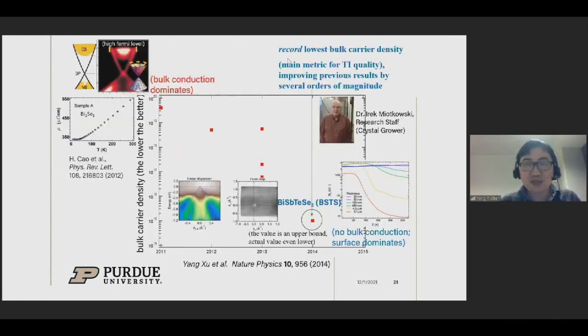So one challenge in the early days of these topological insulators is that the bulk, in fact, contained a lot of unintentional doping. So you can get a beautiful band structure ARPES image like this, showing the entire Dirac cone and part of the bulk conduction band. But when you measure its electronic properties, it's very metallic, with most of the conduction coming from the metallic bulk.